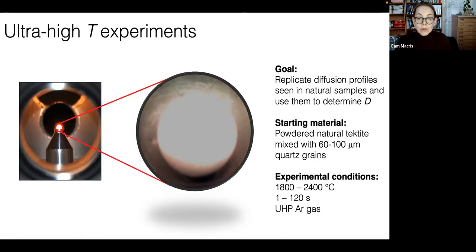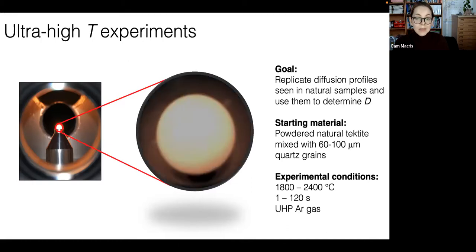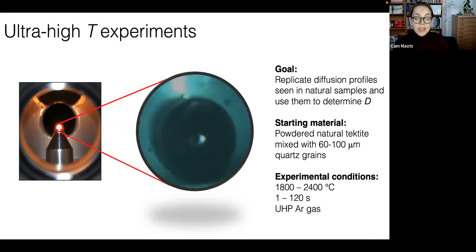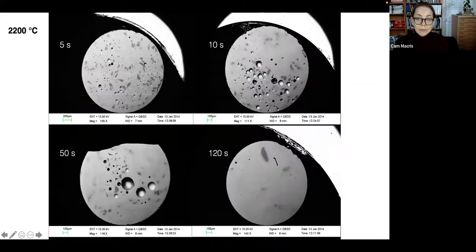We started with a powdered natural tektite where we added in some small quartz grains. We heated these samples to temperatures between 1800 and 2400 degrees Celsius from 1 second to a couple of minutes. And the levitation gas was an ultra high purity argon gas. And what you're seeing here is the sample is fully molten at this point. And in just a second, it should quench. Let's see if we can be patient and wait for that. Here we go. We turn the power off to the laser and it's now cooled. It's a glass again. So it happens very quickly.